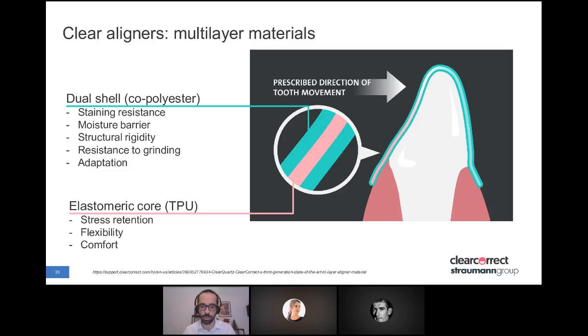as the two skins of the sandwich, which provides a barrier against staining media and also against water. It provides a certain structural rigidity and also resistance to grinding, and provides adaptation. And in the middle, there's an elastomeric core, thermoplastic polyurethane. And this provides a certain flexibility, which is good for the comfort, and also a high ability to retain the stress.